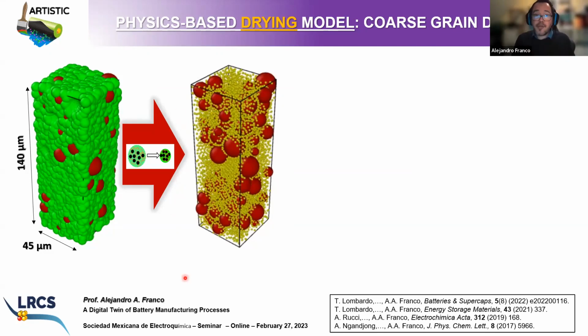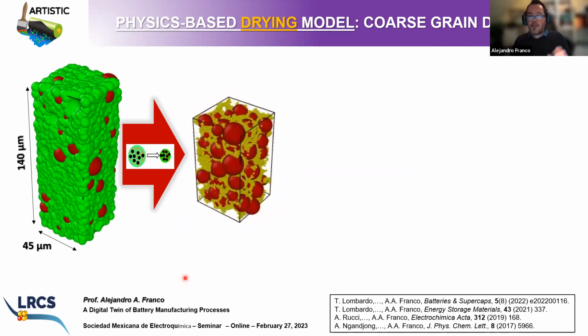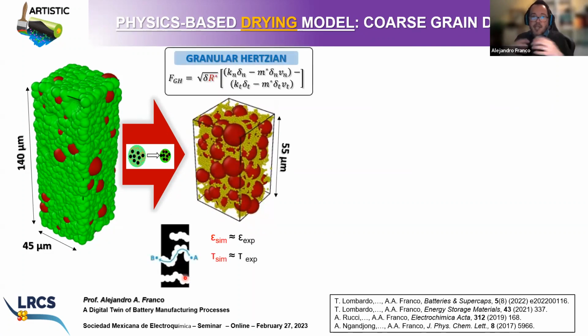And then we run the MD-like, molecular dynamics-like framework again by solving Newton equations, once again describing the interaction forces between the particles, and then we converge to a new equilibrium state, which will represent the dry electrode microstructure, where you see in yellow the carbon binder domain, in this case not containing any more solvent. It contains just carbon additive particles and binder, and you see in red the active material particles with different sizes.